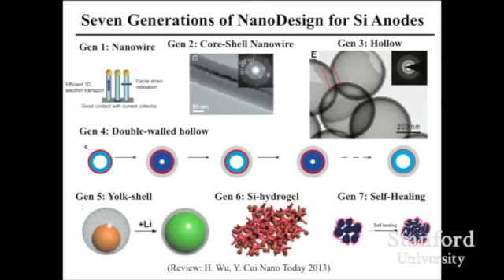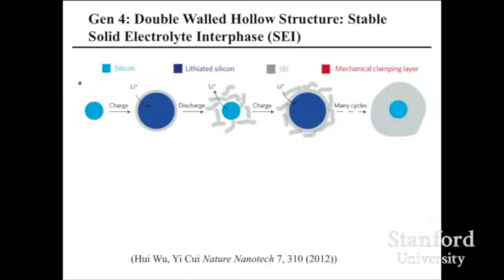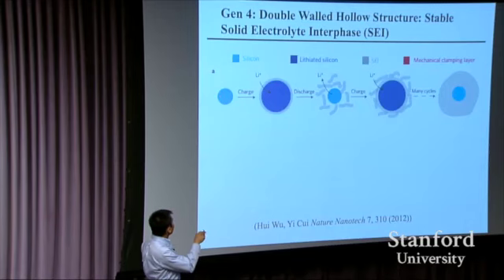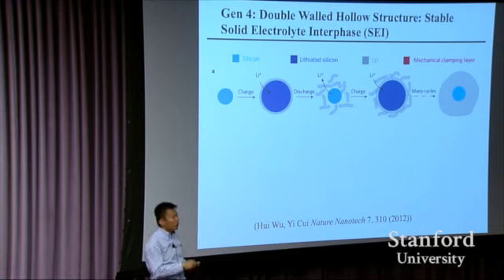Let me show you the remaining critical problem. It's actually the solid electrolyte interphase. Our understanding has been, if you make the particles small, they don't break, so the breaking problem is solved. So what about the solid electrolyte interphase? If you have a silicon particle, even if it doesn't break, you put lithium in, it expands. It's going to react with the electrolyte, forming this SEI layer. If you take lithium out, it shrinks. This surface is not stable. This surface coating will be broken. And then you charge it up again, and you're going to reform this SEI.